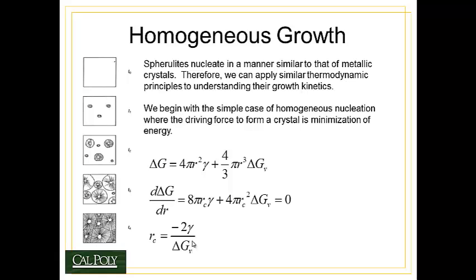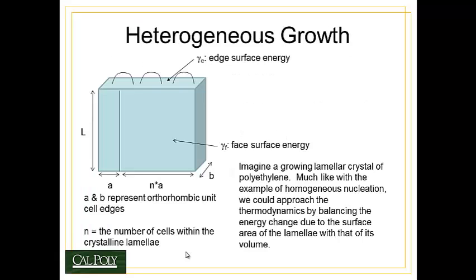In other words, for very small nucleates, they will be unstable until they reach this critical nucleate size where the surface area of the nucleate no longer dominates the free energy volume, and the free energy volume now reduces the energy more than the energy increase due to the surface area of the nucleate growing.